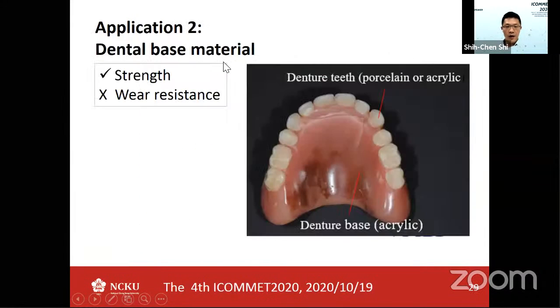Okay. How about the second application? This is the dental base material. The acrylic is over here, and because this will be put into your mouth, the biocompatibility is very important, and the strength of the acrylic is already good enough. However, the wear resistance should be improved, because your teeth and your food will cause some damage and wear on this acrylic. So we're trying to improve the wear resistance of this acrylic.